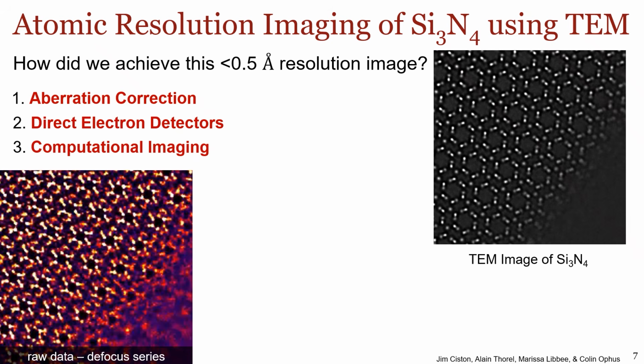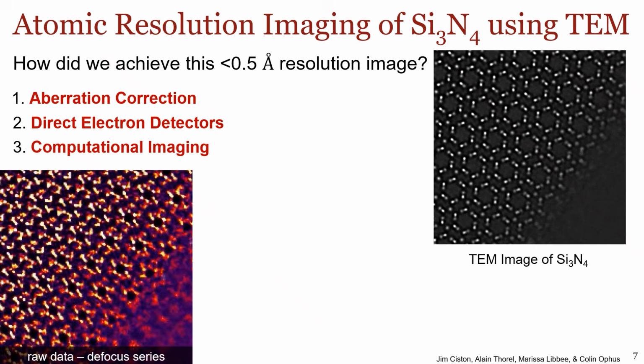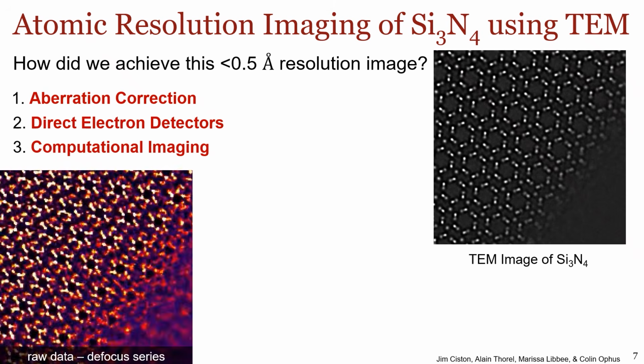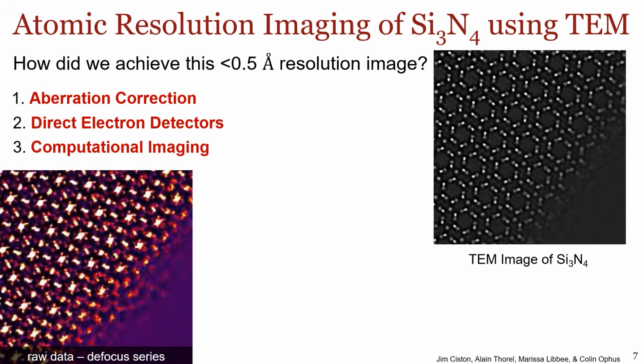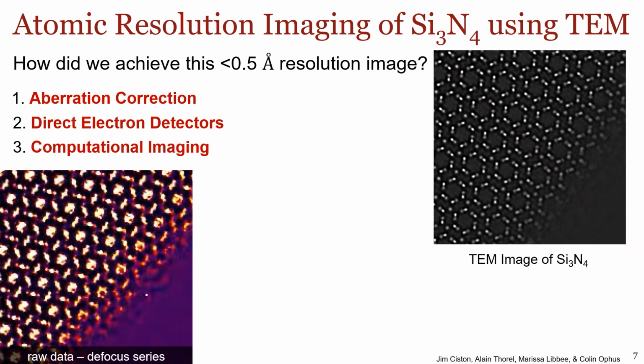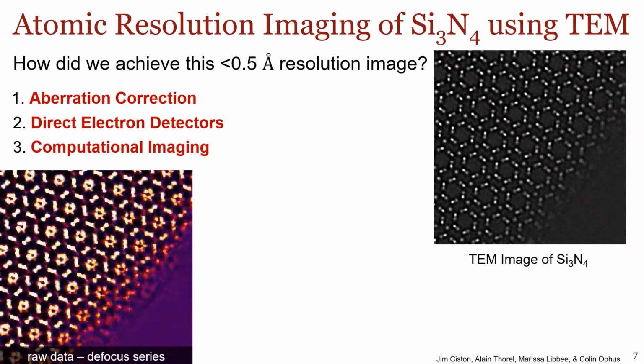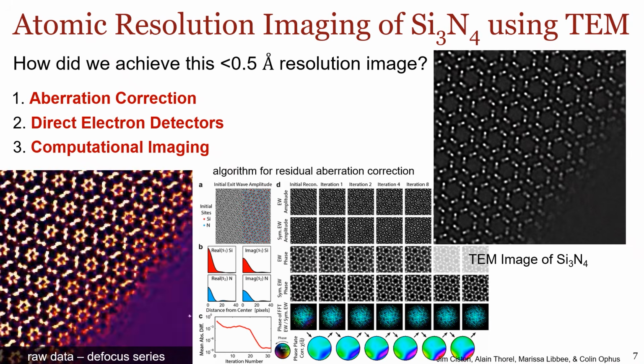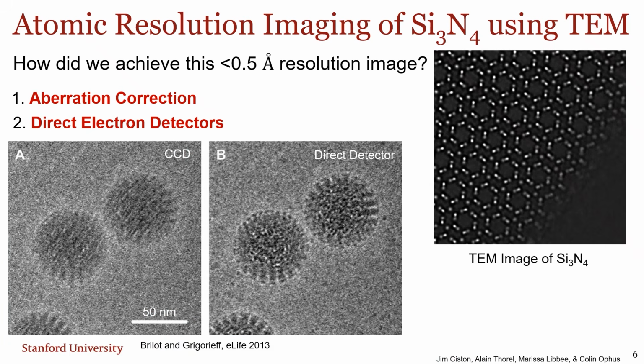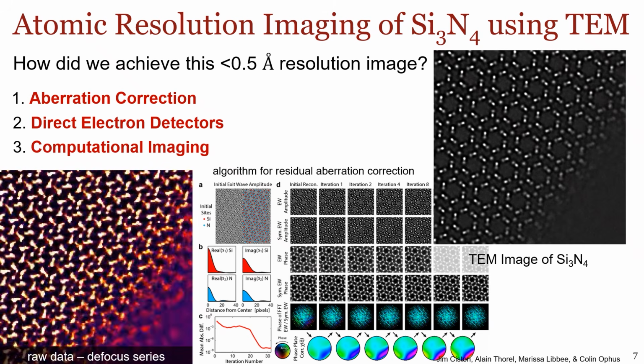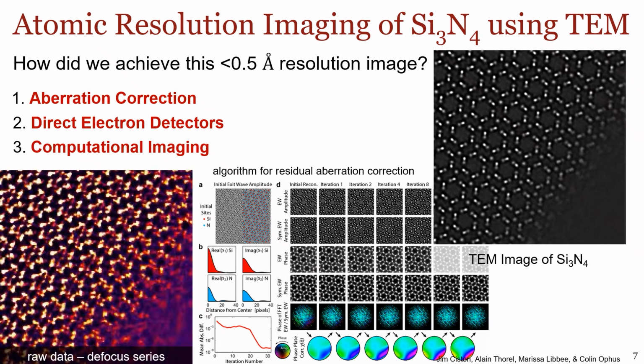But there is a third technology that I would argue is equally, if not even more important going forward, computational imaging. So this is a movie of what the raw data looked like that generated the image in the upper left. So this is what we would call a focal series, where we're changing the defocus of the microscope and we're collecting the sort of different ray paths under different imaging conditions, and then using computer algorithms to synthesize it together into an image. So those previous 2 images I showed you were essentially photoplates and a CCD, but now it's a computer that's taking in the raw data and reconstructing the image here.